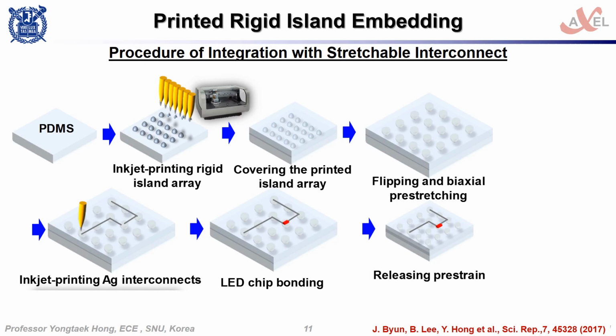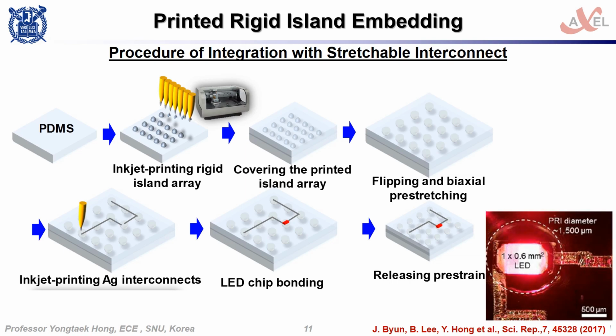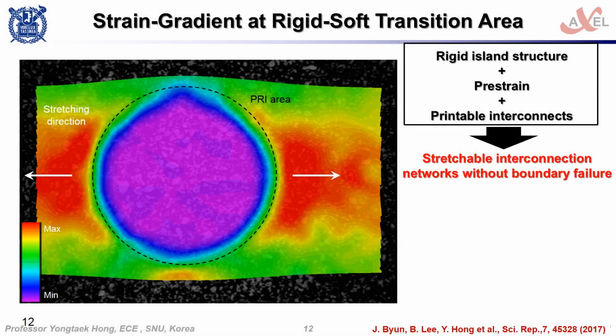We embedded the printed rigid islands in elastomeric substrates in order to control strain distribution when the substrate undergoes mechanical deformation. On the rigid island area, electronic components such as LEDs or silicon ICs are placed, and the stretchable electrodes that are formed from pre-stretching and inkjet printing processes interconnect those components as shown in this figure. As shown in this slide, the printed rigid islands effectively suppress tensile strain applied to the components and protect them from electrical failure caused by the external mechanical deformation.